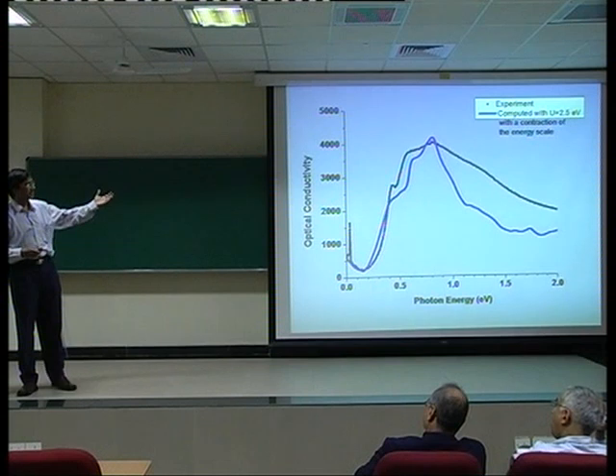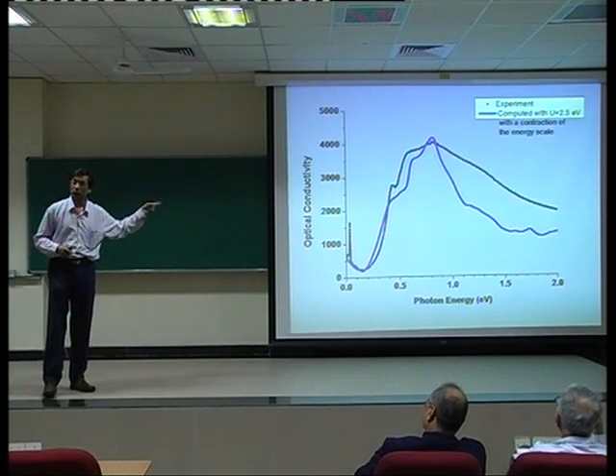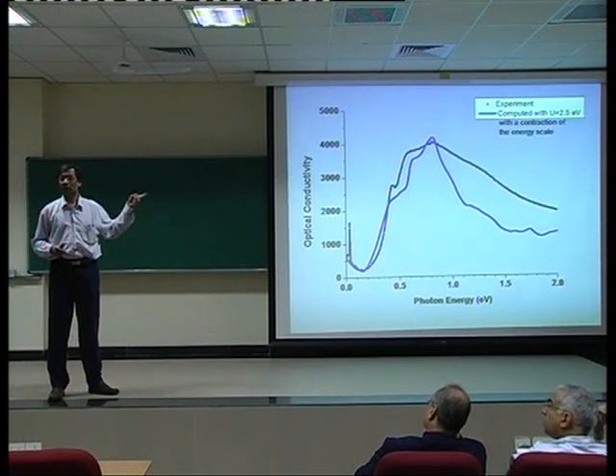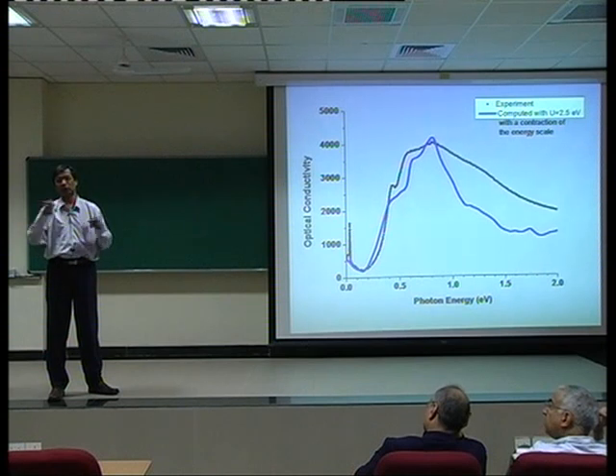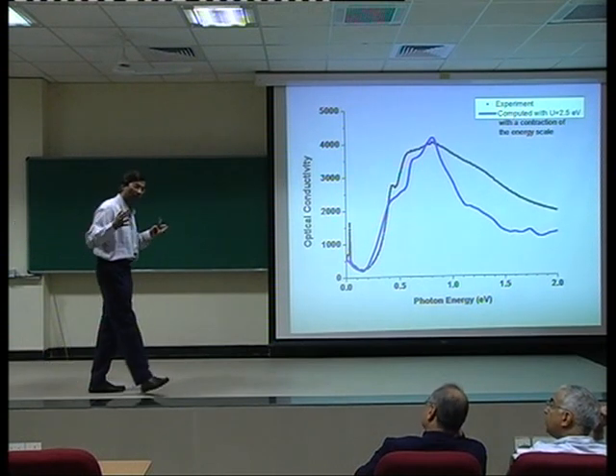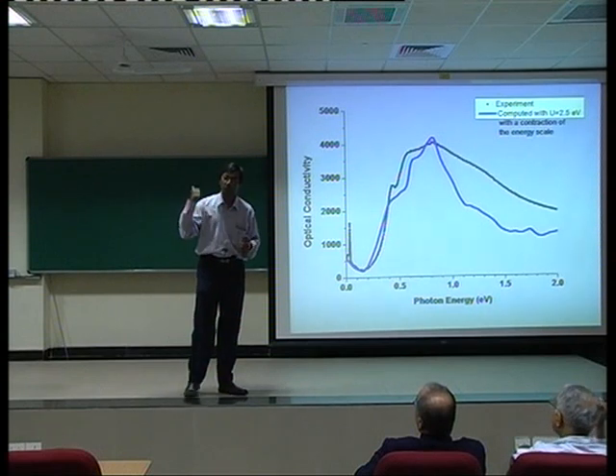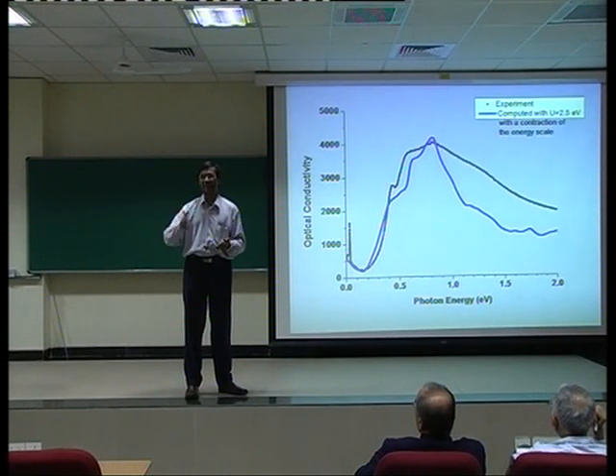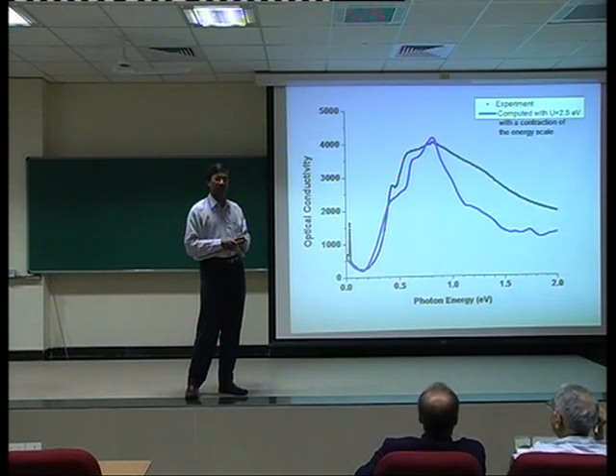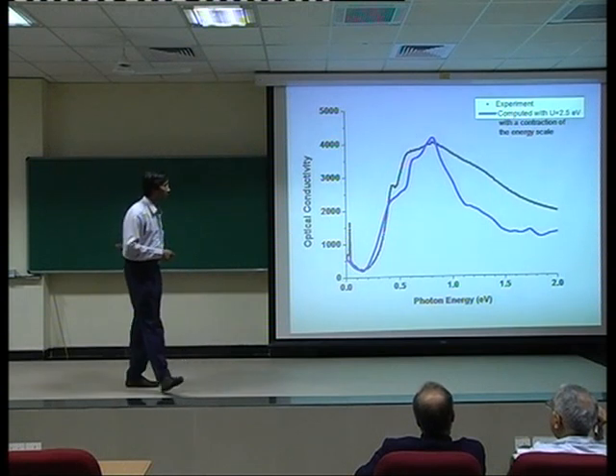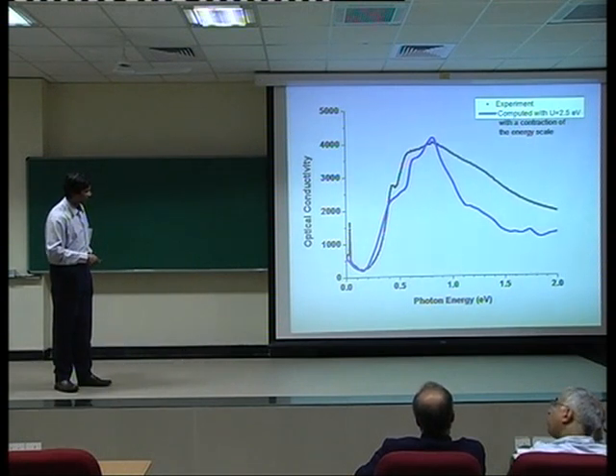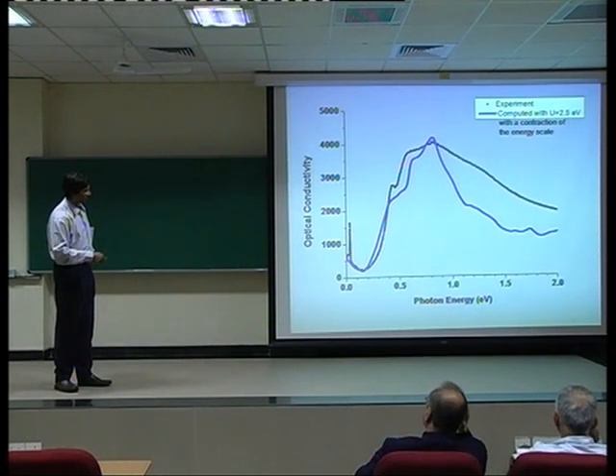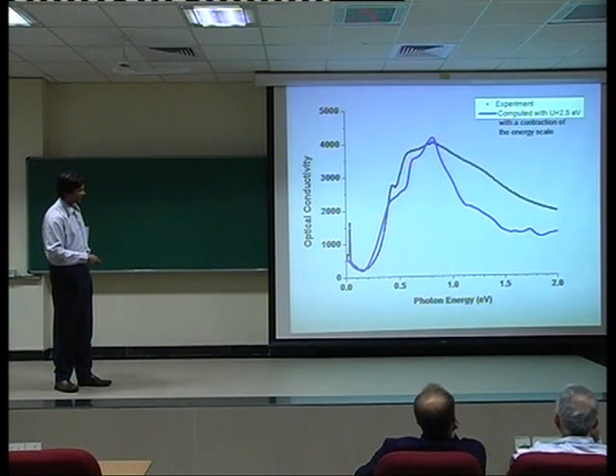Because it's an excited state phenomenon that you're looking at, what is more complicated here is that you will have Coulomb interaction between the electron and the hole. That would again give rise to contraction. So one knows that one needs to contract the energy scale. What we have done is calculate exactly as it comes out from the results and then do a contraction of the energy scale. This is the experimental data, and that's our calculated data with a 30% contraction of the energy scale.